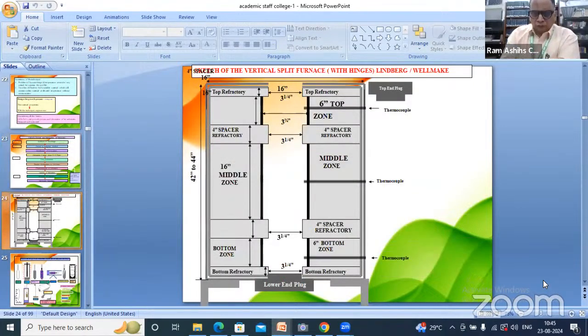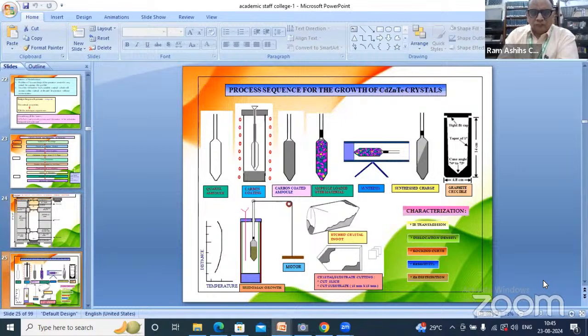This is the design of the old furnace used in the crystal growth process. We have taken a quartz ampule and we do carbon coating in a furnace at 900 degrees by cracking of acetone. It is done to avoid sticking of the high purity material to the inner surface of the quartz ampule. After carbon coating, we do degassing of this ampule, and then we weigh the charge cadmium, zinc, and tellurium with zinc 4% stoichiometrically, place this charge in the ampule, place it in a quartz and seal it.